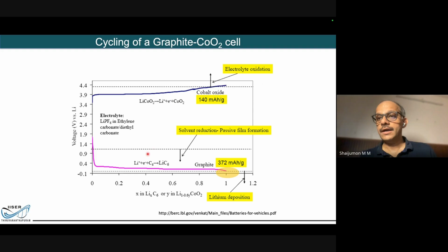Okay, can I then go down? Answer is no, a big no, because again, here is the dotted line. If I go beneath that, what will happen is lithium, instead of intercalating in between these graphite layers, would start depositing as metallic lithium, which is dangerous, because if the lithium starts depositing, it will start creating needle-like structures, which are called dendrites. I have better slides later on, which I can explain further. But just take my word for that, these are dangerous, right? Because these needle-like creatures can pierce through your separator and short your battery, blast.